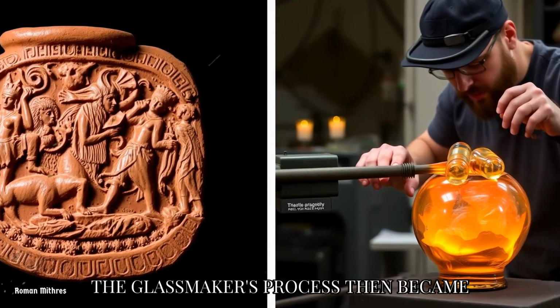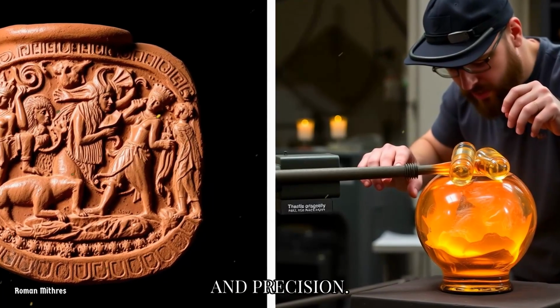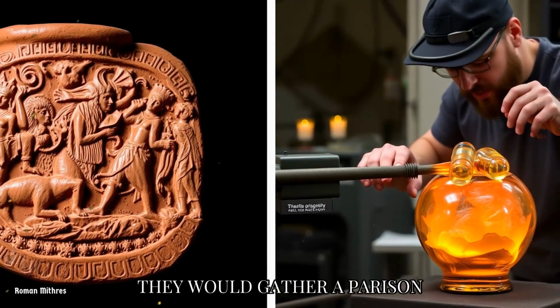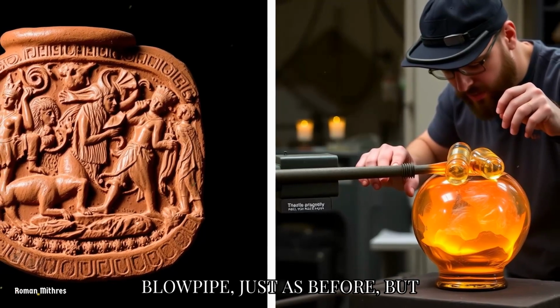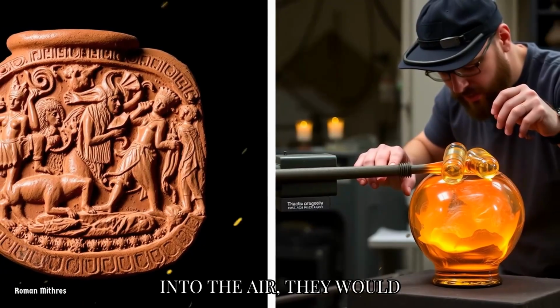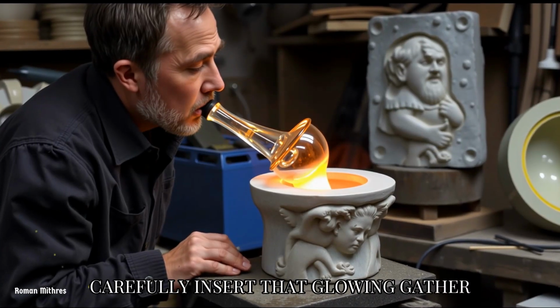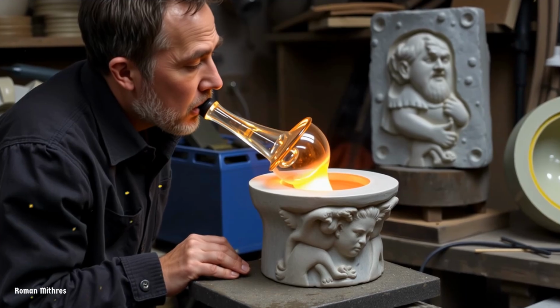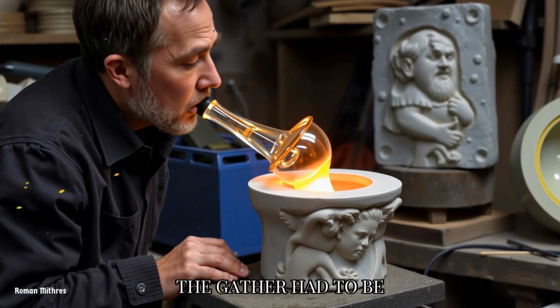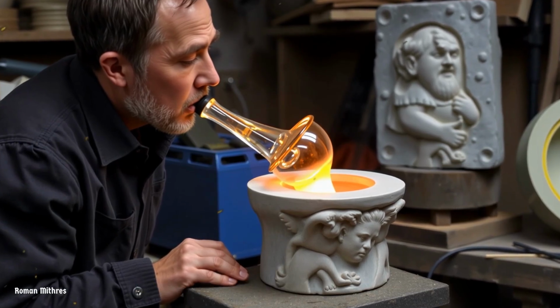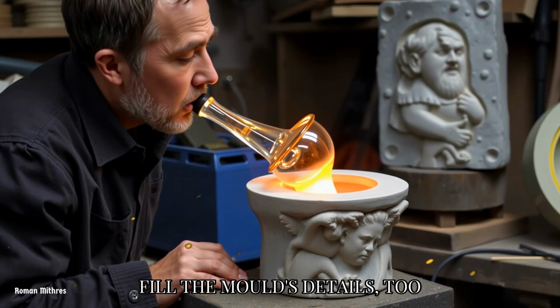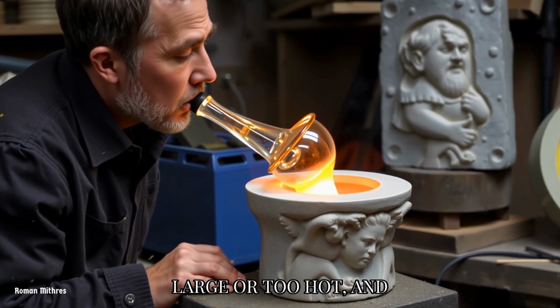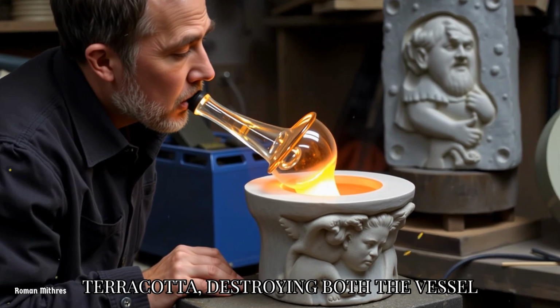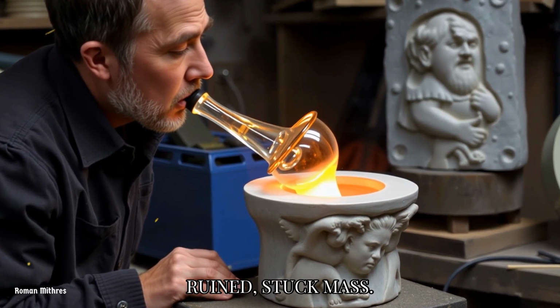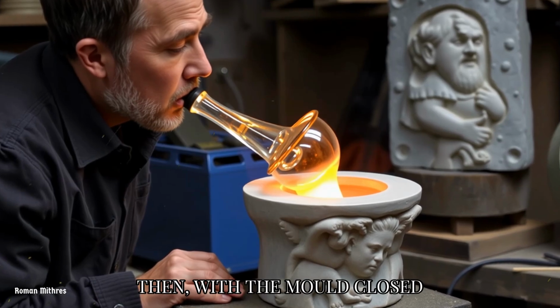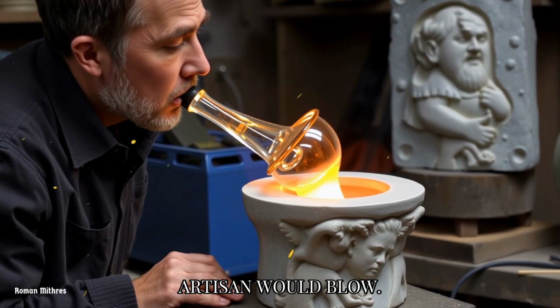The glassmaker's process then became a breathtaking act of trust and precision. They would gather a parison of molten glass on the blowpipe, just as before, but instead of blowing it freely into the air, they would carefully insert that glowing gather deep into the waiting mold. The moment of insertion was critical. The gather had to be the perfect size and temperature. Too small, and it wouldn't fill the mold's details. Too large or too hot, and it would fuse to the terracotta, destroying both the vessel and the mold in a ruined, stuck mass. Then, with the mold closed tightly around the pipe, the artisan would blow.